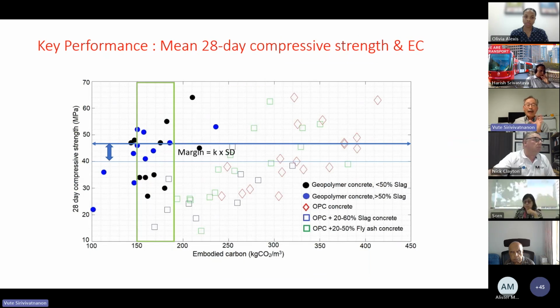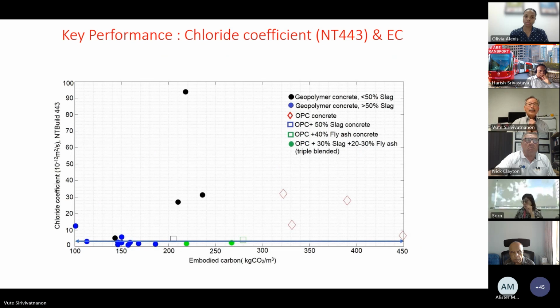And I would also show you just a couple of sets of data, showing the relationship between the different geopolymer concrete and a range of other concrete with SCM on the embodied carbon with respect to strength and some durability. Just an example. In this case, the circles with the darker color, whether black or blue, represent the geopolymer concrete. And you can see that for the sort of strength we are looking at, geopolymer concrete would give a much lower embodied carbon than the sort of concrete that I've just shown you in terms of concrete with high SCM. So it's a very good start in terms of strength.